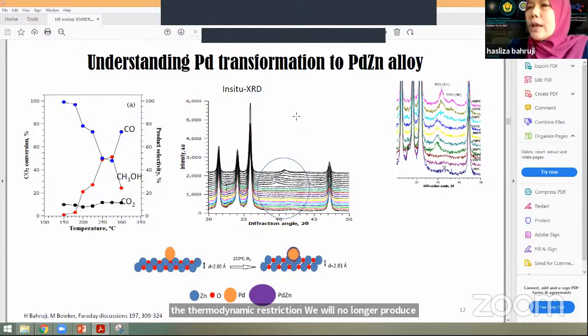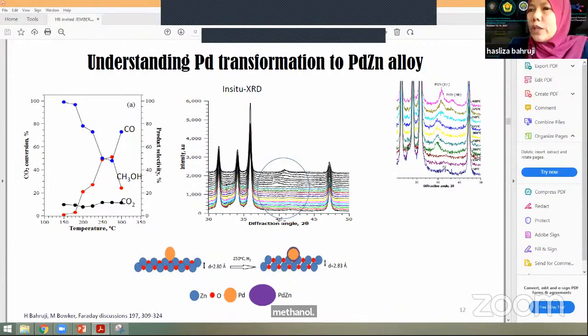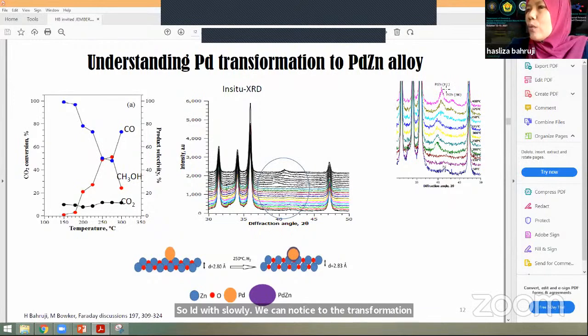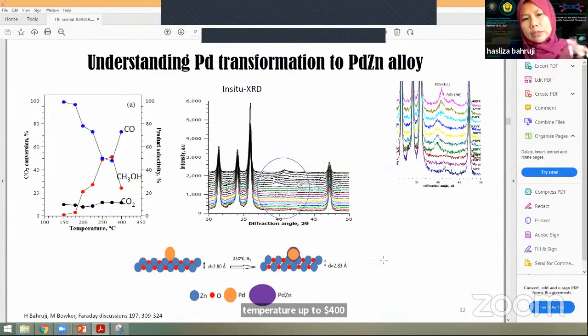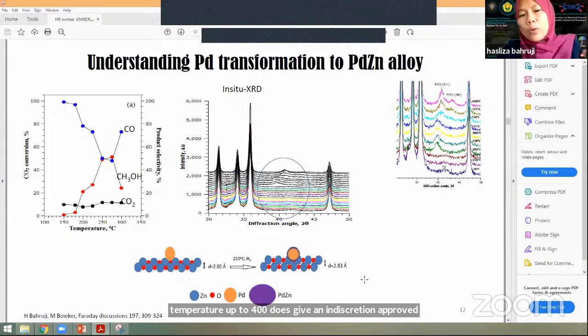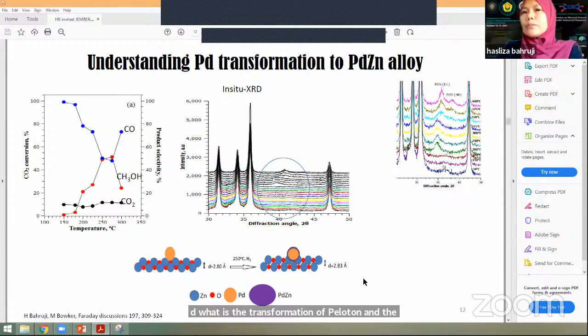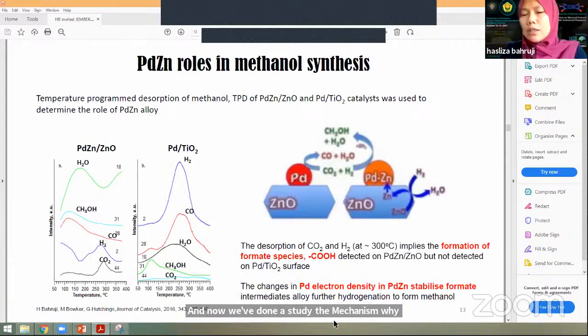So when we look at the in situ analysis using XRD, we can slowly see the transformation of palladium to palladium zinc alloy when we increase the reaction temperature up to 400. That gives us indication, a proof basically, of what happened to the catalyst when we carried out the reaction from 150 up to 300. The important part is the transformation of palladium nanoparticles to palladium zinc alloy. And then we're going to study the mechanism of why this is very important.